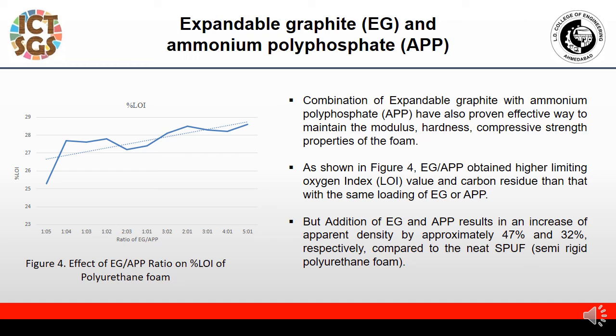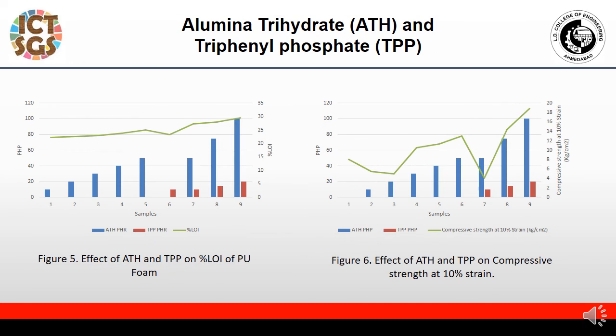But here the addition of EG and APP results in an increase in the apparent density by approximately 47 and 32% respectively compared to the neat semi-rigid polyurethane foam.